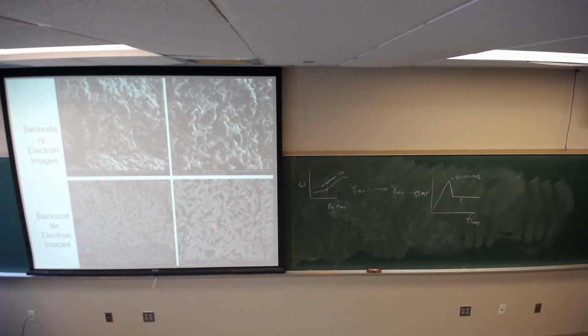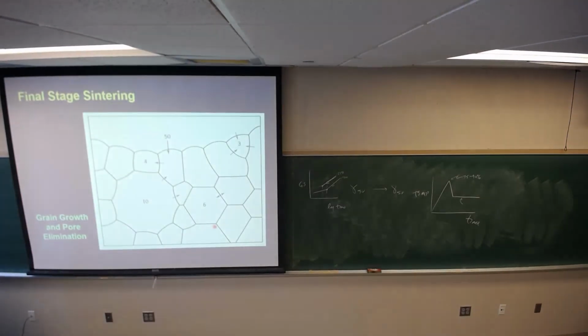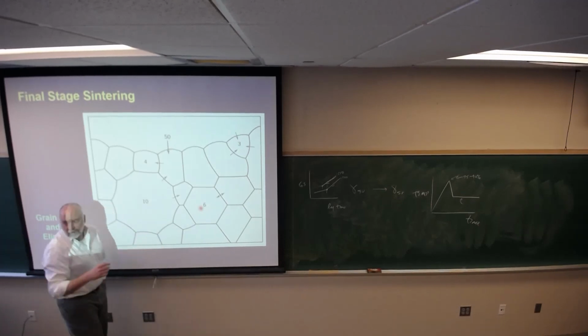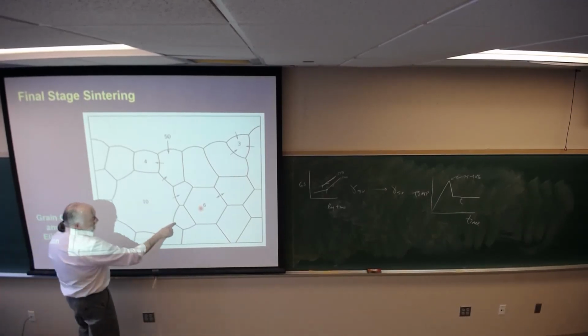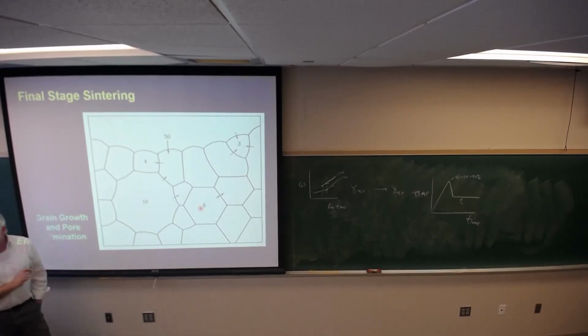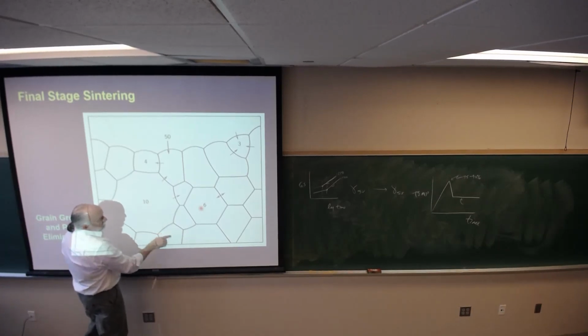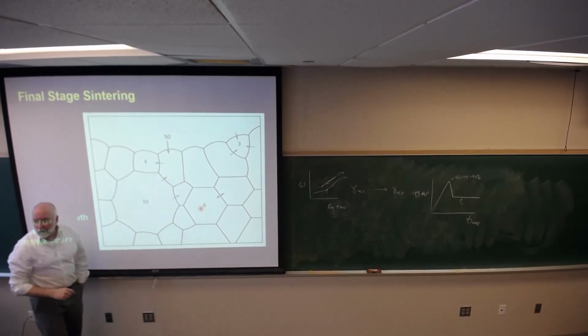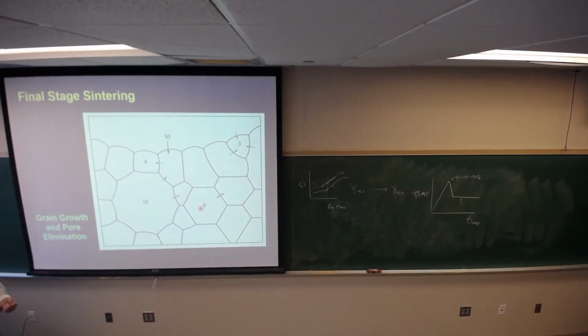Okay. So, where does that leave us? That leaves us to final stage sintering, and the argument is that curvature dictates whether a particle or a pore will grow or shrink. I like this image because you don't know what's a pore and what's a grain. It turns out it doesn't make any difference. If I look at 6 here, all the curvature is flat. That means there's no movement of the grain boundary. But here, where I have a curve, it says that the grain boundary wants to move in what direction? Yeah, it wants to move this way, right? So if I do that, this grain will eventually disappear, or that pore will eventually disappear. So the coordination number around these particles or grains or pores dictates whether they're going to grow or shrink.